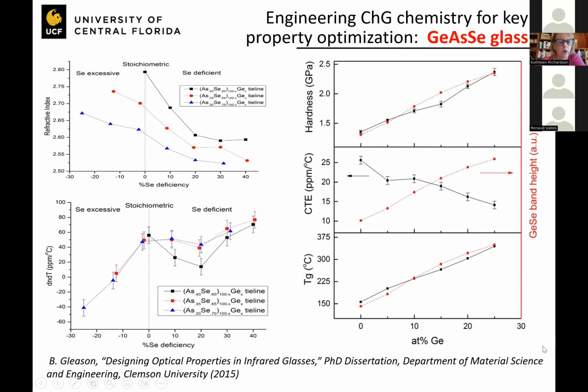where he showed that by relating through Raman spectroscopy the constituencies, in this particular case the intensity of the germanium selenide Raman band, could be used, as a function of germanium content, to engineer not only the glass transition temperature, the coefficient of thermal expansion, the mechanical properties, but also, by understanding what the impact on these constituents was depending on what the stoichiometry of the material was, either having excess chalcogen or group 6 element, in this case selenium, or a deficient amount, how the key aspects of, in this case, index and thermo-optic coefficient, or dn/dT, changed as a function of these.